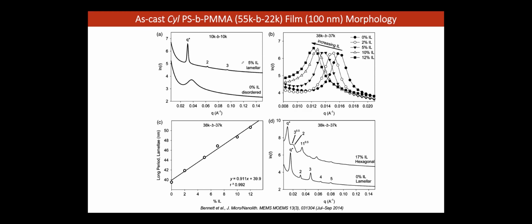ionic liquid. And the reason is chi goes up because the ionic liquid is a preferential good solvent for the PMMA block, all right? So then the interaction with polystyrene goes up. So you can use ionic liquid to tune block polymer interactions for sharpness of the interface as the main theme, and in fact, to bring order into disorder, which is a really nice thing.